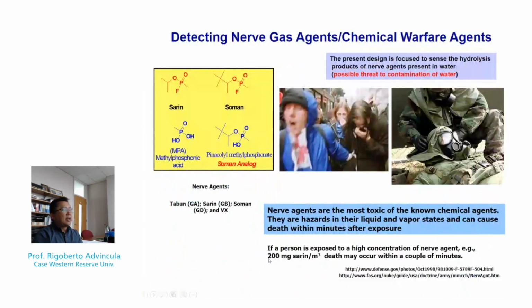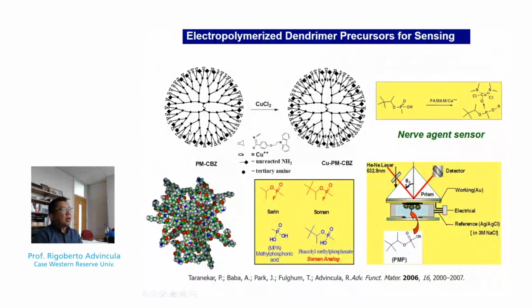Now, another experiment we did is in a series of sensors using molecular imprinting. In fact, one of the papers we reported was based on a dendrimer that was electropolymerized on an SPR electrochemistry setup for the detection of a nerve warfare agent analog, because I don't want the real thing in my lab or close to my students. So we use this model to polymerize a dendrimer on top of a gold substrate surface. This dendrimer has copper ions that can complex with an analyte such as these sarin and soman analogs or methylphosphonic acid. The bottom line is this is an SPR experiment with an electrochemistry setup for deposition of the dendrimer film, and then we use this for sensing.